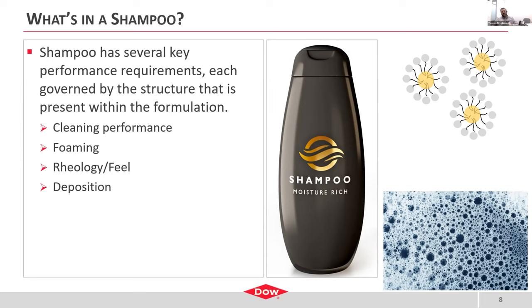Additionally, these amphiphilic materials like to migrate to the surface. They have a component in them, that greasy hydrophobe, that doesn't like to be in the water. So they can migrate to the surface, therefore lowering the interfacial tension and the energy barrier between oil and water. And what that does is that will allow that soap or that material to foam. You want to generate that thick, foamy lather while you're in the shower. That's a way to do it, by having these surfactant systems in there.